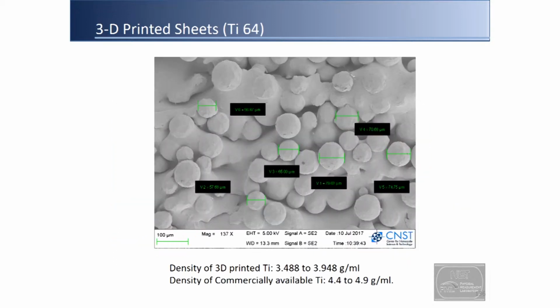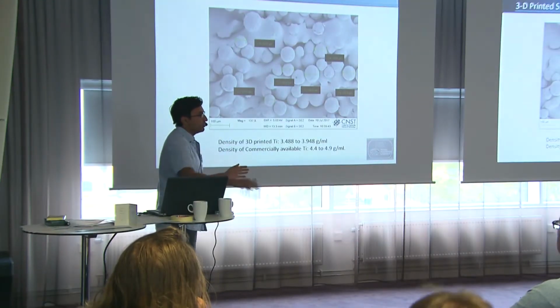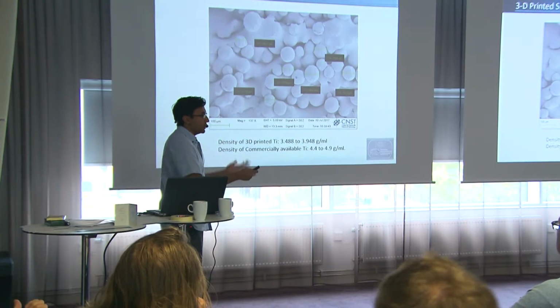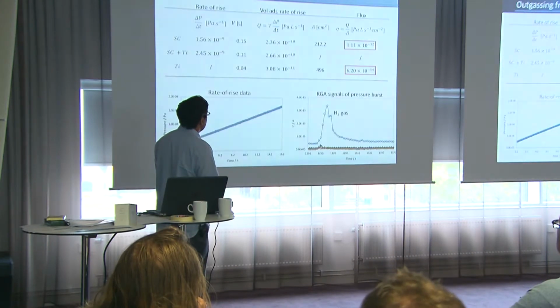So here's an SEM, and this is really what concerned us right from the beginning. You see the SEM, you see all the voids, you see the density drop. So we were worried about water molecules. Are there waters trapped somewhere, so they're going to have a long outgassing rate, and that's going to destroy your vacuum over time? Because we want to get to a very low level and then stay there while we do experiments and have our instrumentation work for a long time period.